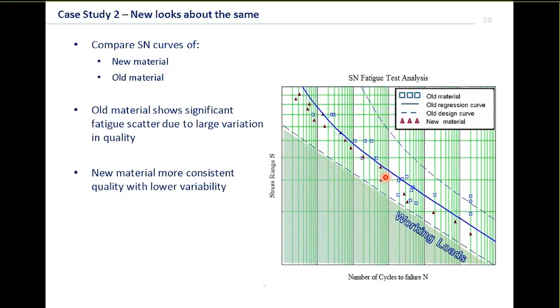Now with this material, which was based on a real example, the customer didn't know all of the loads. However, they did know that in the past 15 years, no components had failed. So we can start to work out statistically, based on this data, if no components have ever failed, then we're pretty sure that our working loads must be below this area, because statistically, with a good confidence, we should have seen some failures if they were higher than that. So effectively, we're using statistics just to try and work out where the working load range is. It's somewhere down here.